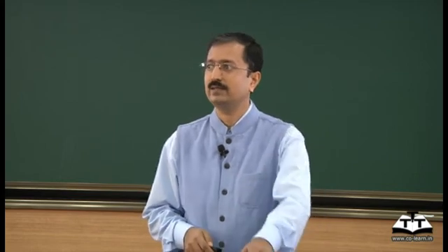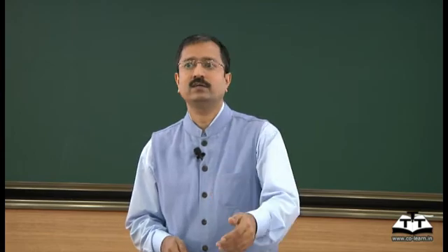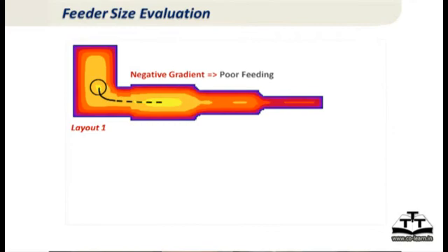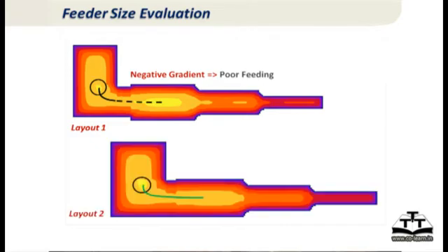Calculation does not guarantee that feeder size is right — it is only a starting point. End of the day, you have to actually put thermocouples or simulate the casting and verify that the hot spot is shifting to the feeder and that the feed path is available from feeder to casting. If the feed path is not available, no matter how big a feeder you put, if it is placed in the wrong location it is not going to help, because the feed path will not be taken care of.